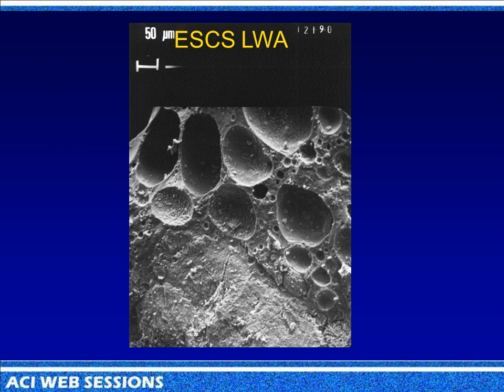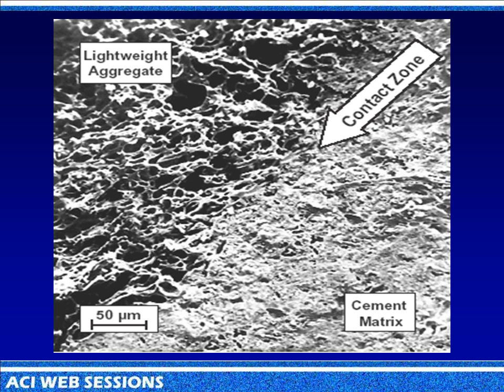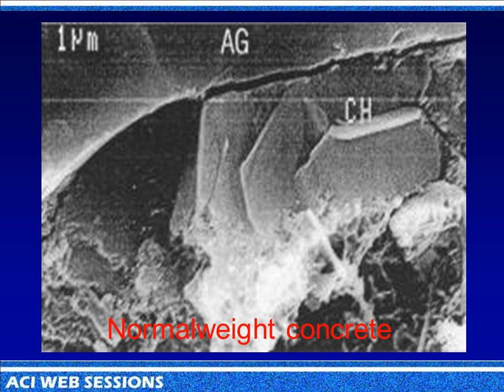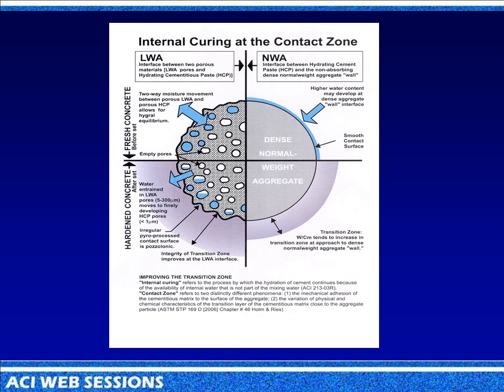So you take a look at this. Here's a great example. This is a lightweight aggregate. Here's the cement. You can see this bond between them. Here you get a closer look. They're almost welded together. And in contrast, you look at here. Here's an aggregate particle, normal weight. And here's the calcium hydroxide, the cement. And almost always you're going to find a clear demarcation or a clear, sometimes even a micro crack at these surfaces.